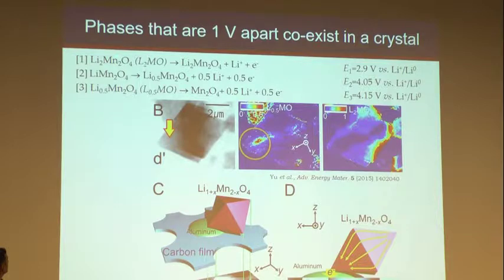You can actually start from a lithium 2 state, which is all manganese 3, and that's how we actually started the experiment. And this equation should be a 1. You can remove one lithium and go from lithium 2 to lithium 1. This happens at 2.9 volts. So if you then want to know what the free energy is, you multiply by Faraday constant and the number of electrons. If you keep going, you can remove another lithium, and that happened in 2 steps, just like I showed you for the nickel phase. You get a 0.5, and then you get a lithium 0. And those happen at 4 volts, very close to each other, only separated by 100 millivolts.